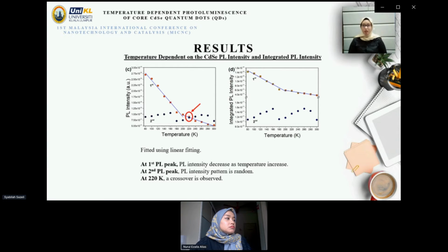The PL spectra of cadmium selenide quantum dots will be investigated to understand the radiative and non-radiative emission processes with respect to temperature changes. Generally, at high temperature, a semiconductor demonstrates low PL intensity compared to low temperature. This is because of an increase in non-radiative phonon interactions. As the temperature increases, numerous free excitons are released from the bound state, which causes the emission to gradually disappear.